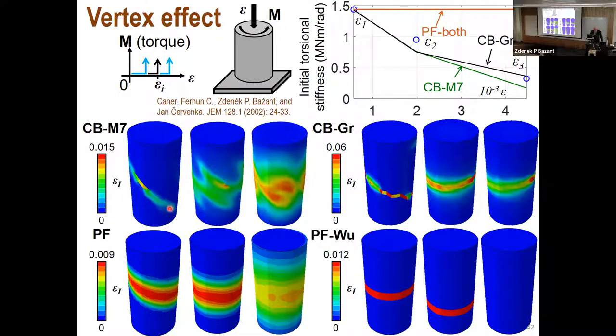Now another test which is overlooked and also ignored, actually, on metals. We know that if there is a theory of plastic damage with loading surfaces, the loading parallel to the loading surface must be elastic. All right, so if you take a cylinder and load it axially and then apply torque, so this axial strain, apply torsional moment M. We'll look only at the initial stiffness. So at various levels, before peak, at peak, after peak.